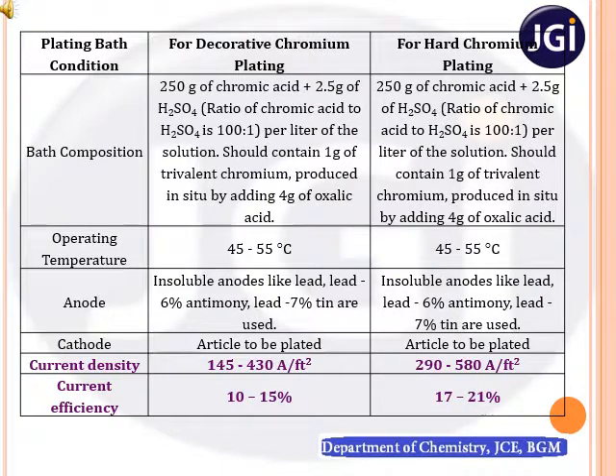The plating bath composition and conditions are given below. Here we are discussing decorative chromium plating and hard chromium plating simultaneously, because the bath for decorative and hard chromium plating remains the same. The only difference between the two is the coating thickness. If the coating thickness is less and restricted to 0.75 micrometer, then we call it decorative chromium, and if the thickness increases beyond 0.75 micrometer up to 300 micrometer, we call it hard chromium. The process for both cases is the same. The only difference is the restriction of thickness.